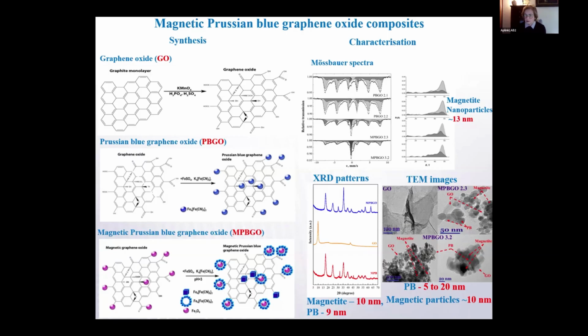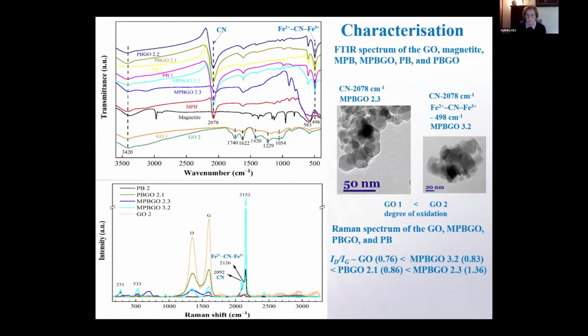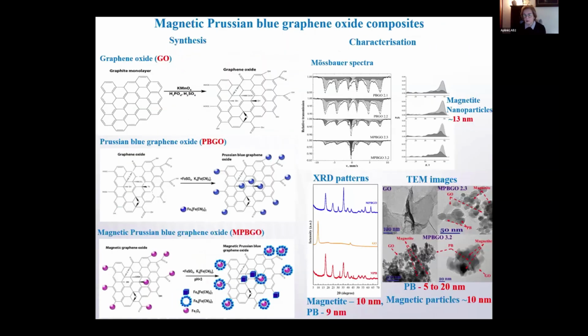So magnetic Prussian blue composites were synthesized, and again they were characterized using Mössbauer spectroscopy, XRD, and TEM. Our results showed that Prussian blue particles were uniformly distributed on the graphene oxide sheets.